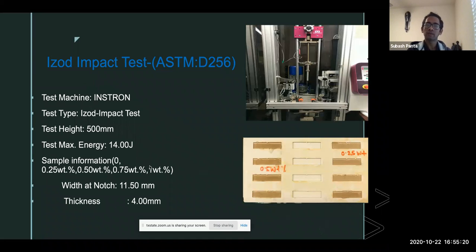Next one is the Izod impact test, which was done according to ASTM standard D256. The test was done in an Instron machine, test type Izod impact test, height 500 mm, test maximum energy of 14 joule, and samples were fabricated with a loading level of 0, 0.25, 0.50, 0.75, and 1 weight percentage. The sample width at notch is 11.50 mm, thickness of 4 mm.